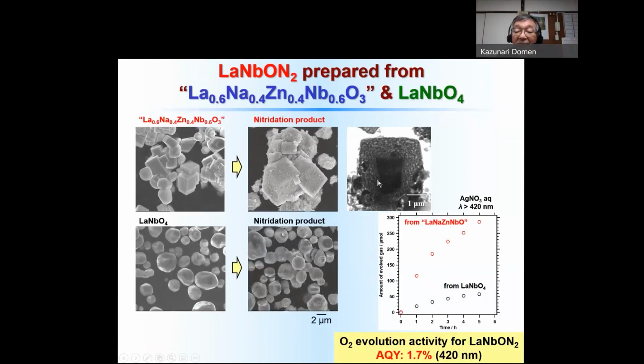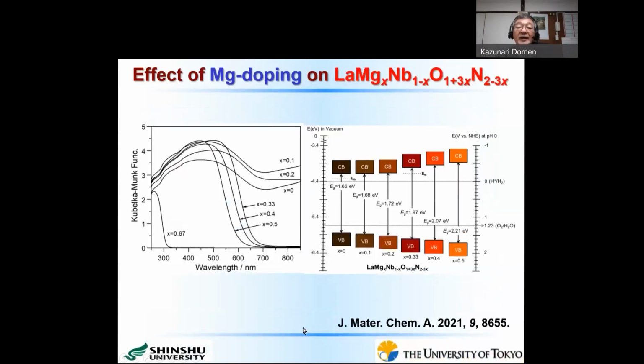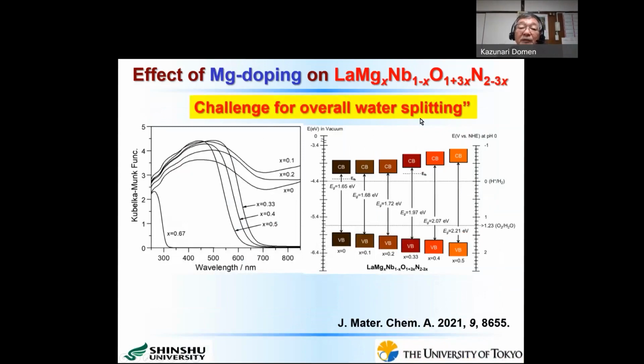However, when we examined the O2 evolution activity, this is the previous data, and this is this data, and as you see here, the apparent quantum yield was improved to about 1.7%, more than 2 times higher than the previous one. Then we decided to challenge the overall water splitting reaction.